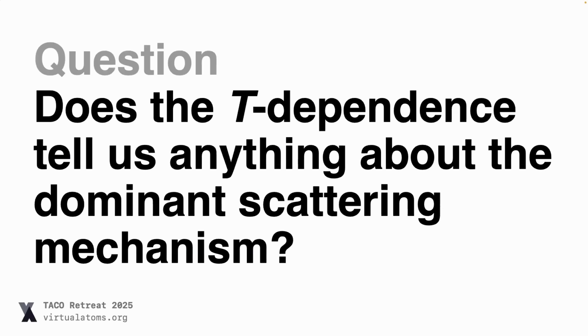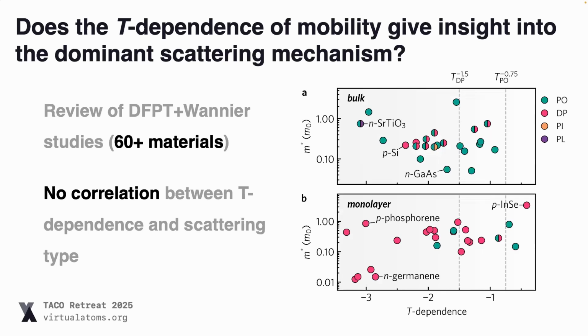And so we wanted to answer this question: does the temperature dependence of mobility actually tell us anything about the dominant scattering mechanism? The first thing we did is a review of all of these high-quality calculations that have been performed to date, and this is what we're showing here. On the x-axis, we've just got the temperature dependence, and on the y-axis, we've plotted them based on effective mass. The different colours of the points show what mechanism is dominating. So for example, the pink is the deformation potential, and the teal is polar optical phonon scattering. What you can see is that for a single scattering mechanism, let's say pink, you can basically span the entire range of temperature dependences from -0.5 all the way to -3. So from this very quick assessment, we thought, it's really not safe to assume a particular scattering type based on the temperature dependence of mobility.